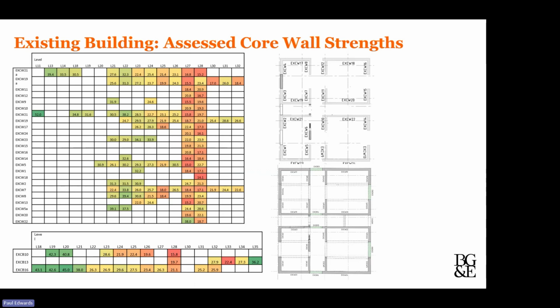So it's worth bearing in mind that the first pass of both the non-destructive and destructive testing was done in a representative manner. So you're talking approximately around, in terms of Schmidt-Hammer, 10 to 12 tests per wall, and then in terms of the cylinders for destructive testing that were taken out, maybe 1 or 2 on each floor level. The decision was, if we'd have just left it at that in terms of trying to understand the existing material, the resultant costs to the project of reinforcing the core walls to achieve the desired strengths of the new build project would have been significant.